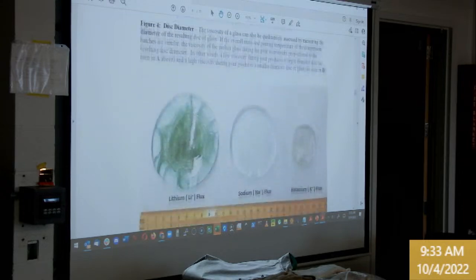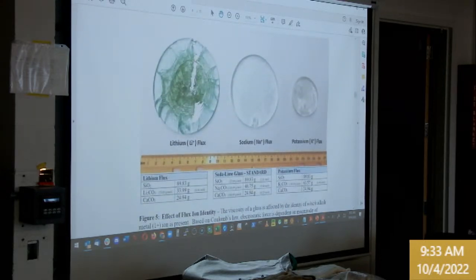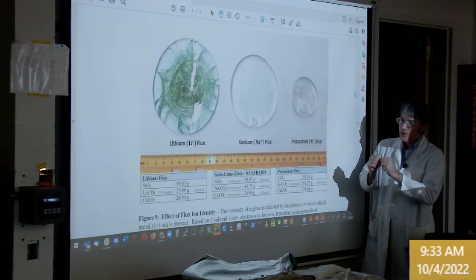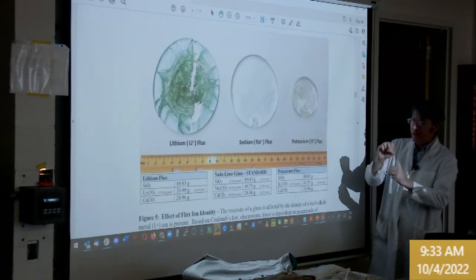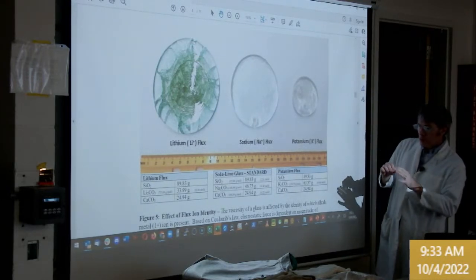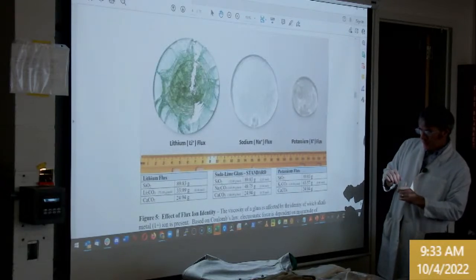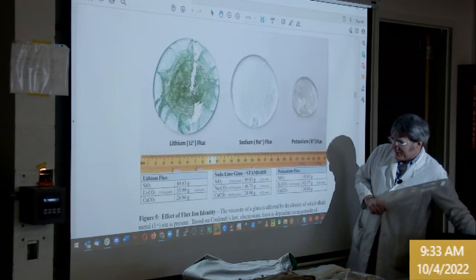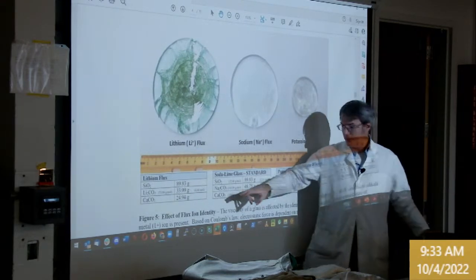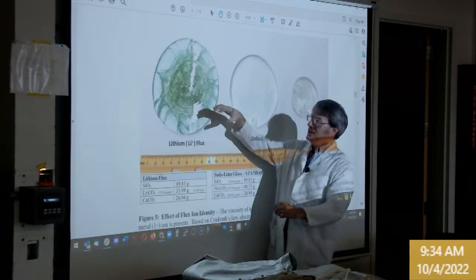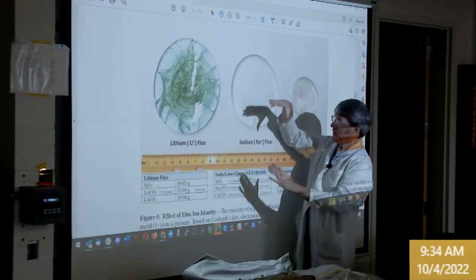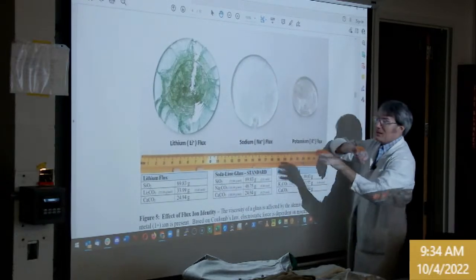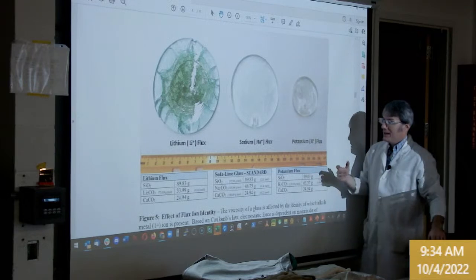High flux, low flux. Here's an example of lithium versus sodium versus potassium. So lithium is a smaller ion, it's a more potent ion, and it moves faster. So for the same molar concentrations of our fluxes, 0.46, 0.46, 0.46, the lithium will be more active, and this one cracked, of course, but you can see that it's spread out to a much bigger disk than the sodium did, and at the same pour temperature, the potassium was a smaller disk.